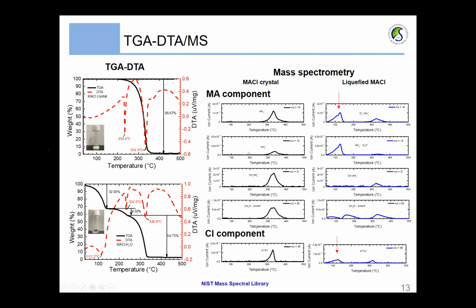To see what is happening at this lower temperature, we also carried out mass spectrometry, and we found that the MA and Cl fragments were detected at this lower temperature, which shows that the MACl decomposes more easily at a lower temperature. So we conjecture that this is the positive azeotropic effect of water, which lowers the boiling point of the MACl decomposition or evaporation.